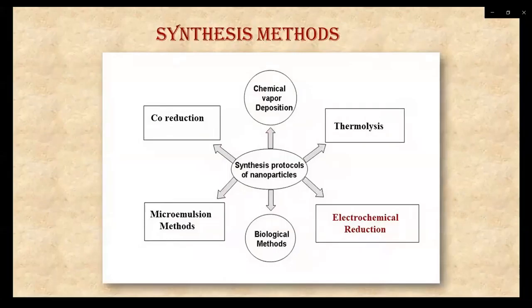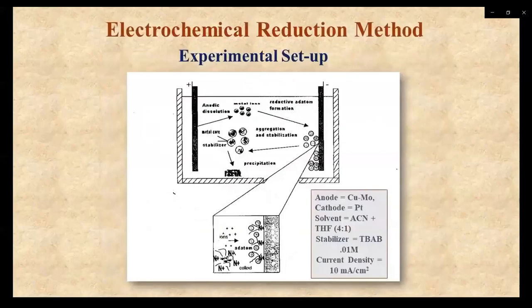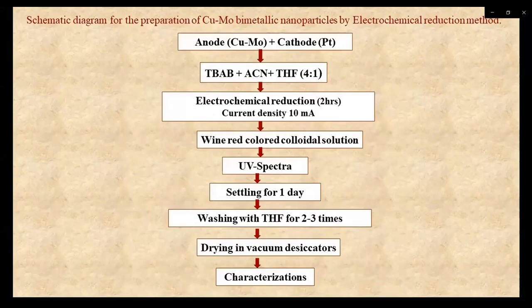These nanoparticles are synthesized by several methods. Some representative methods are shown here. Among all these methods, we used the electrochemical reduction method because this method is very easy and has many advantages over the other ones. And this is a typical experimental setup which is used for the electrochemical reduction method. This setup is connected to the potentiostat, which supplies constant current to the system. This is the schematic diagram for preparation of copper molybdenum nanoparticles by electrochemical reduction method.